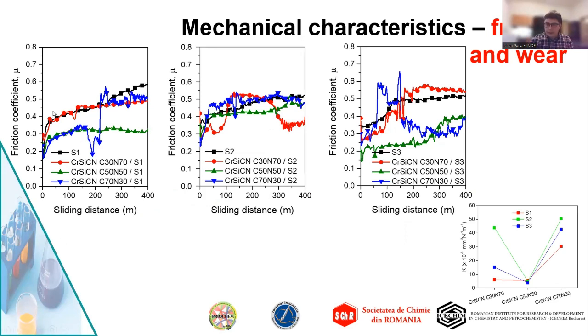The steel substrates are represented here with the black color, and we see that the friction coefficients for all the coatings are below the black curve. But the best result was for the layer with the green color. This is with 50% of acetylene, obtained with a reactive gas flow of 50 standard cubic centimeters per minute (SCCM) of acetylene and 50 SCCM of nitrogen. The other two coatings exhibited an unstable behavior.